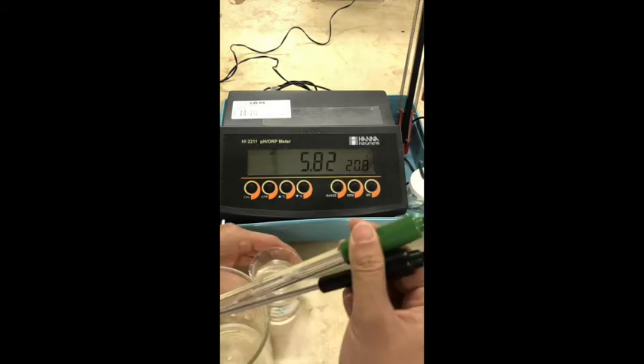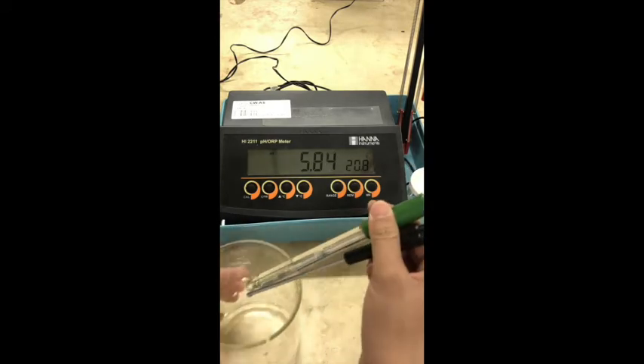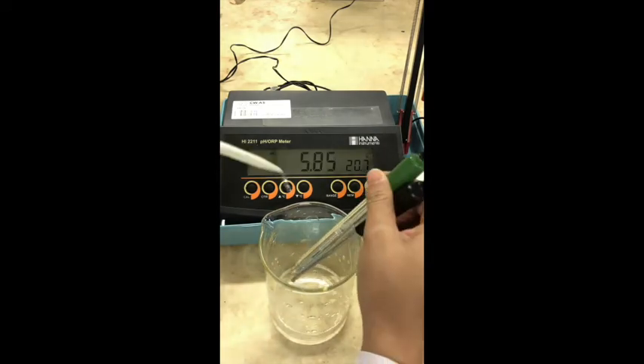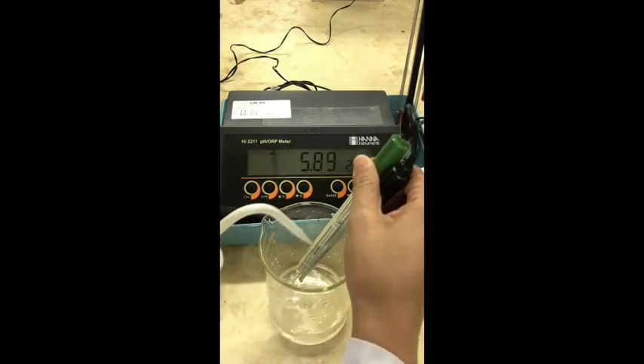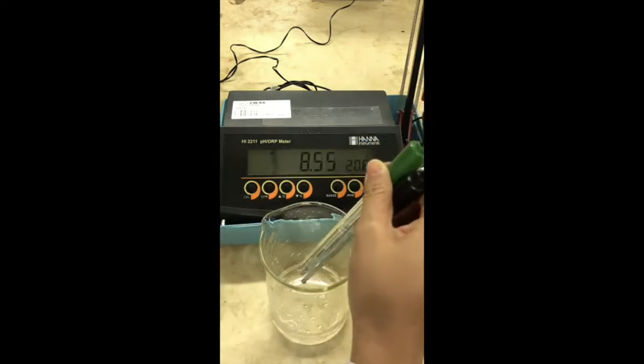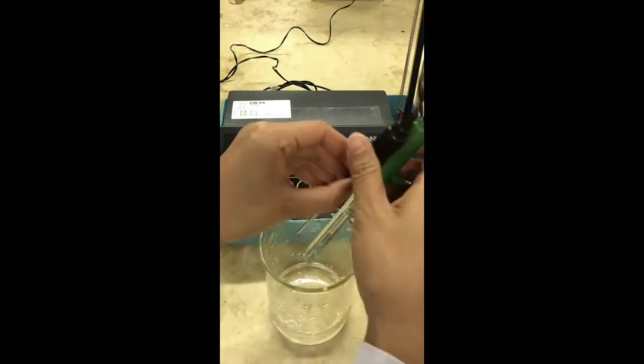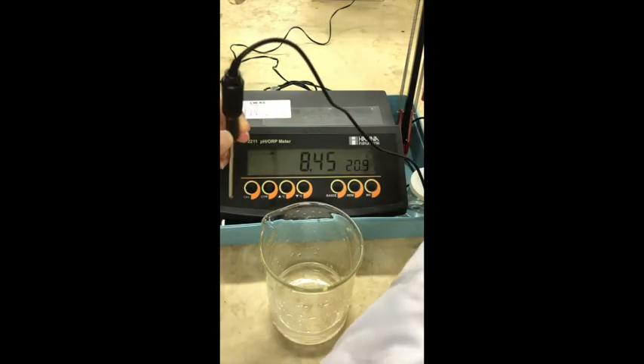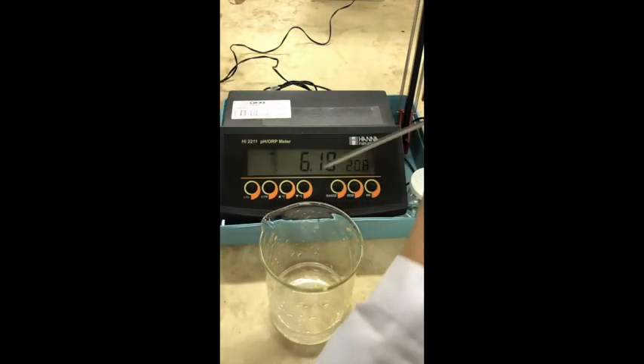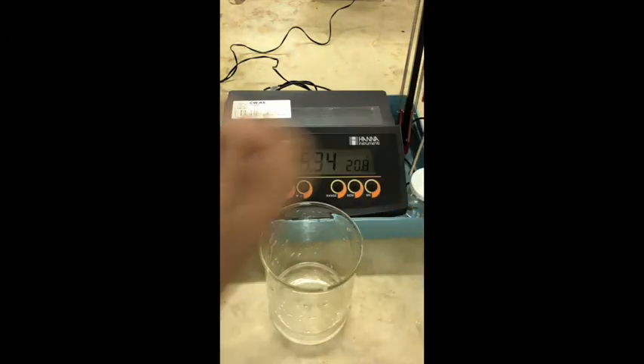After the measurement, remember to rinse the electrode and thermocouple with deionized water. Place the electrode into a bottle containing deionized water. Clean the thermocouple with the lens paper. This is the end of the pH measurement. After the measurement, let's write down our results. The pH of the sample was 5.82 and the temperature of the sample was 20.8 degrees Celsius.